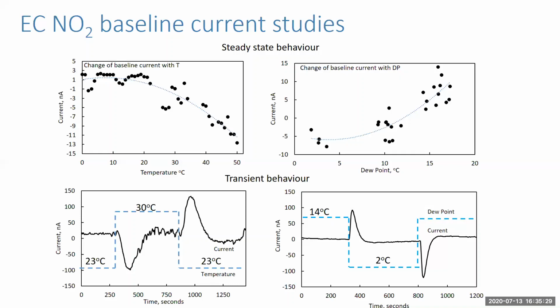However, if you do a step change in either dew point or temperature, you can see a much larger transient effect. So the bottom two graphs show changes in the current in response to, firstly, a step change in temperature of only 7 degrees, and in the case on the right-hand side, a change in the dew point of about 2 degrees to 14 degrees. And you can note that the size of the currents generated by the transient behaviour are significantly larger, perhaps 10 times larger than the changes due to the steady state behaviour. And the question is why this might be. What's generating these very large transient currents?